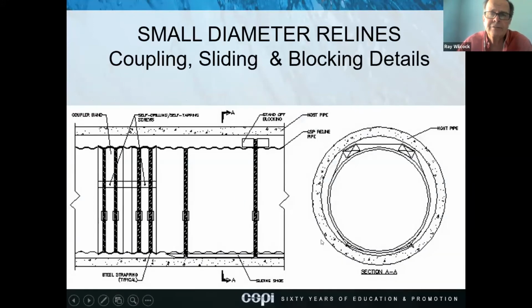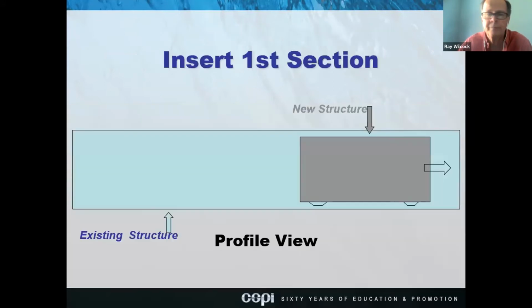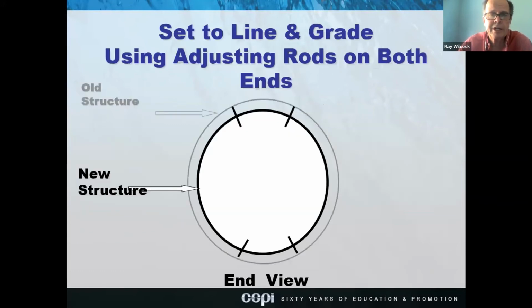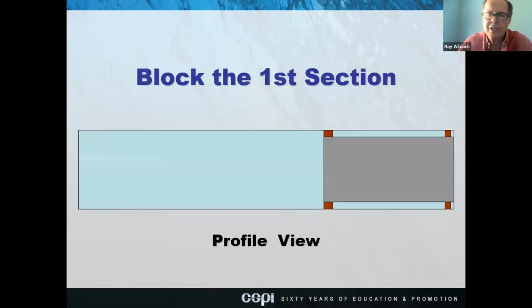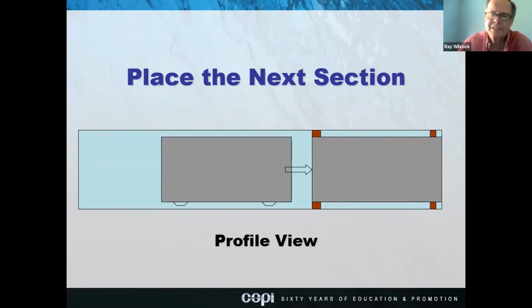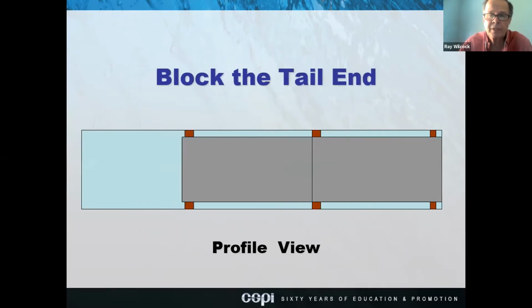Here's a schematic of a small diameter reline showing the coupling, sliding, and blocking details. But I'm going to move forward and keep going. You insert the first section down through the pipe. You set it to line and grade using adjusting rods on both ends. So you see the new structure inside the old structure in an end view. You block the first section, from the top and the bottom. You place the next section up against the first section, and you block the tail end of that second section.